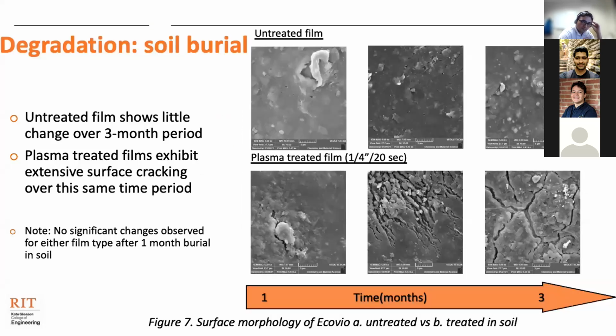Now let's start to talk about the degradation characteristics of these films and how these films perform in the soil and compost. Figure 7 shows six SEM images of the films, which is a good way of determining the surface morphology of the films. The top 3 pictures show 1, 2, and 3 months of an untreated sample, and the bottom 3 images represent 1, 2, and 3 months of a treated sample. As we can see, as time progresses, the untreated sample does not undergo any significant degradation on the surface, whereas there is an appreciable amount of degradation happening even after 2 months in soil for the treated samples, as can be observed by the cracks and tears on the surface.